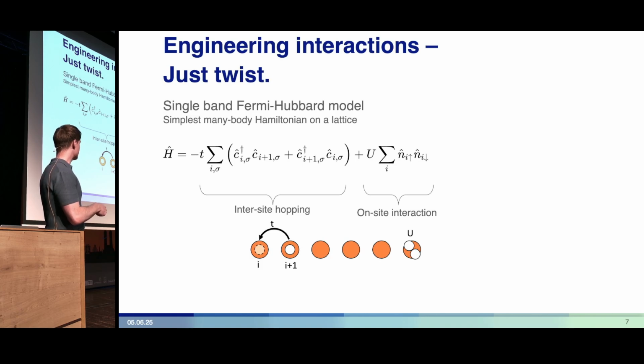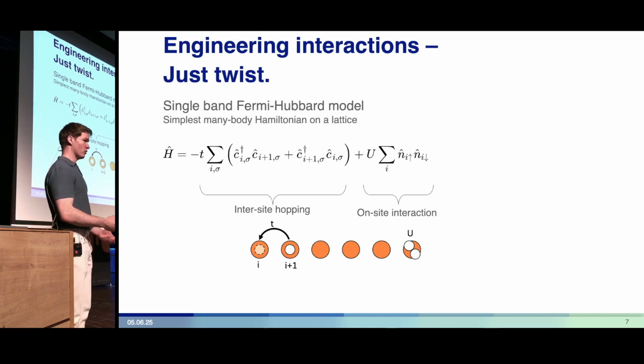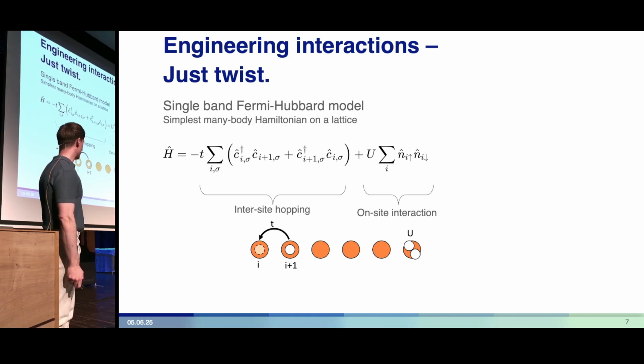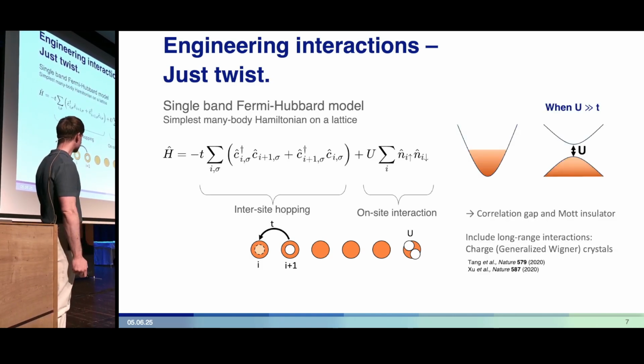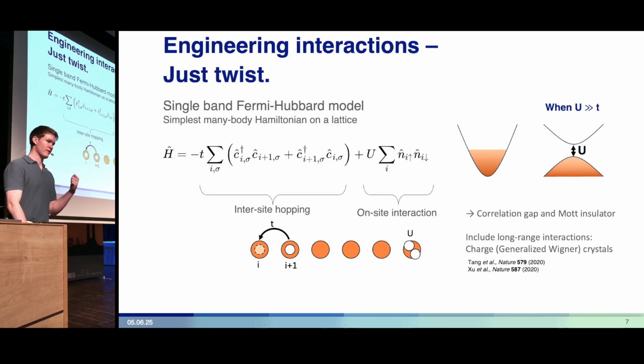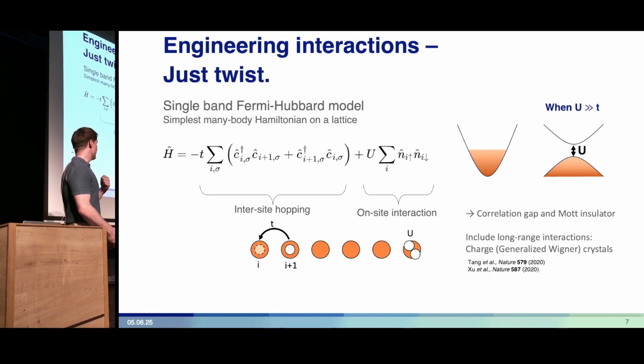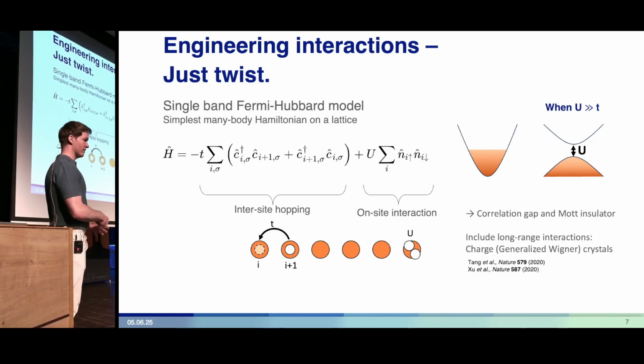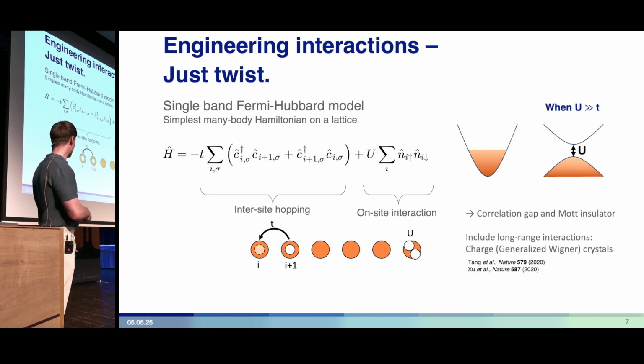Then there's an on-site interaction term, which takes care of the fermionic counting statistics, and it can be repulsive or attractive. In general, we're talking about Coulomb interactions here, so they are usually repulsive in semiconductor systems. But even this very simple model captures some really important first results, the first being that at half filling, normally you would have a metallic state. If I put one particle per lattice site in the Fermi-Hubbard model, without interactions, I expect a metallic state. But if I turn interactions on, repulsive interactions, and make them very strong, U much greater than T, then this metallic state transforms into a gapped correlated insulating state, a Mott insulator.